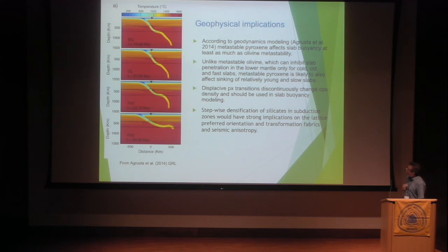In terms of geophysical implications, there was a group of geophysicists, geodynamists who did simulations of how would preservation of pyroxenes in cold subduction zones affect the buoyancy of the slabs, and they found that the effect is stronger than the effect of preservation of olivine. It could be the controlling factor for whether the slab stagnates or not.